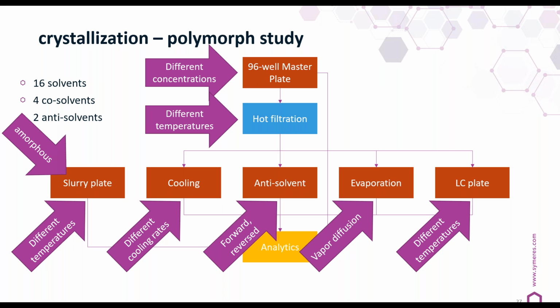start with different concentrations, because that will allow you the difference in your supersaturation and therefore your nucleation behavior. When you do filtration, look at different temperatures. A slurry plate, start with the least stable one, so see if you can find an amorphous form. Also work with different temperatures there. Cooling, work with different cooling rates. It will give you different results, of course.